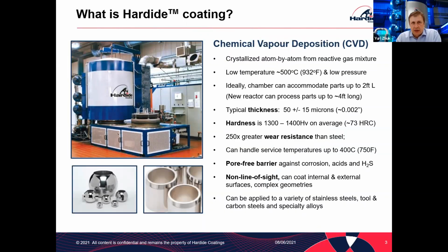To start with, what is Hardide coating? It's a coating produced by a process known as chemical vapor deposition. Essentially, we are using a vacuum reactor, one of which is shown in the photo here, and we have a mixture of reactive gases flowing through the reactor, and every hot metal surface in contact with the gas media has the coating crystallized atom by atom. What that enables us to do is coat internal surfaces, external surfaces, spherical parts, complex shapes, all over non-line of sight areas. That's probably the number one capability or competitive advantage of our technology compared to other hard coatings. We use a low temperature CVD at 500 centigrade.